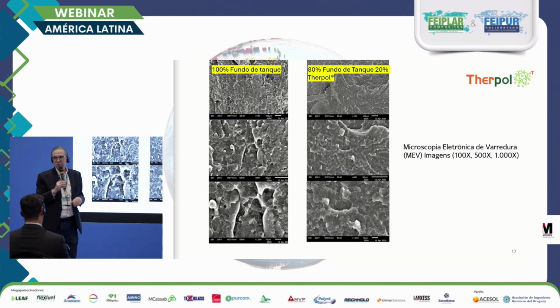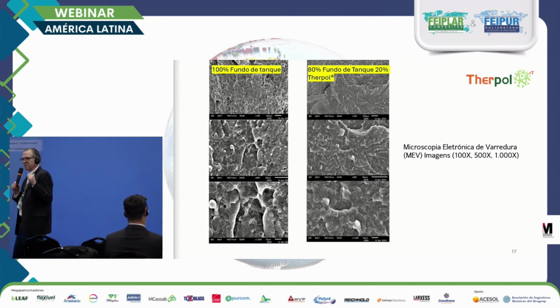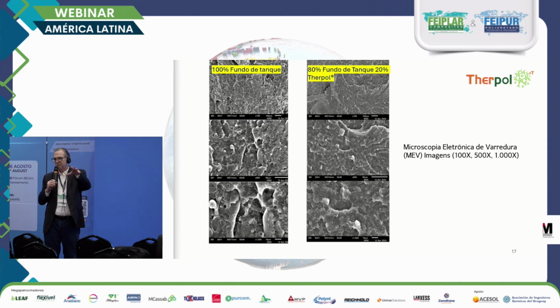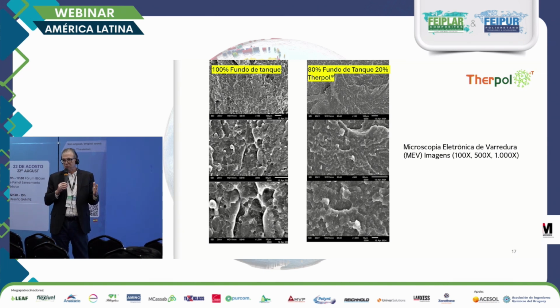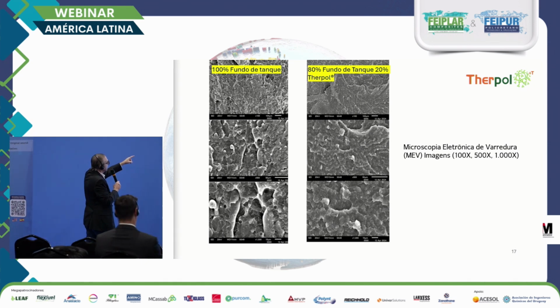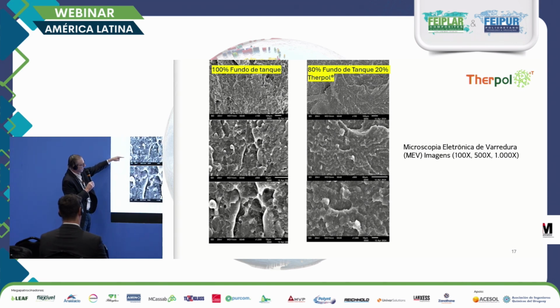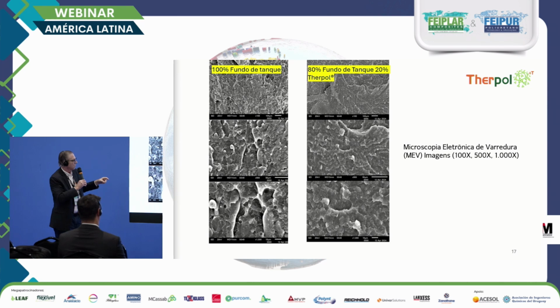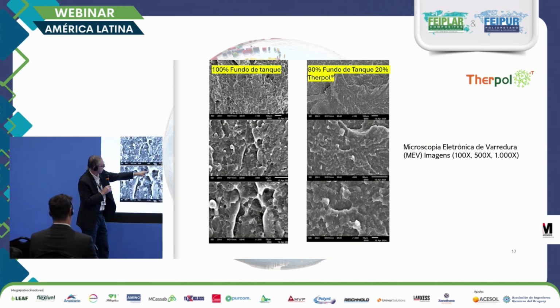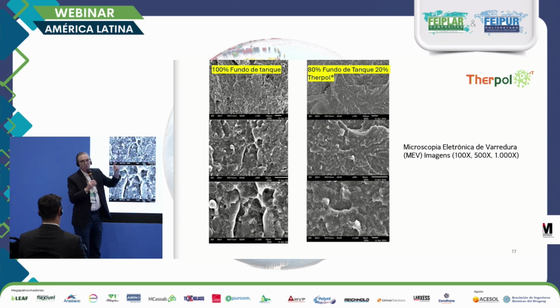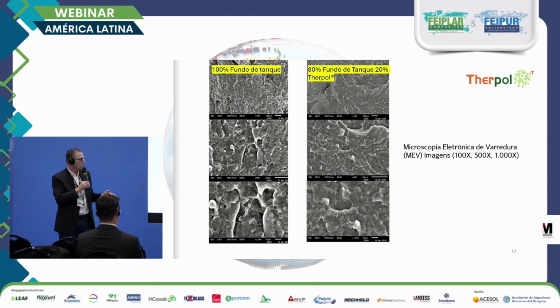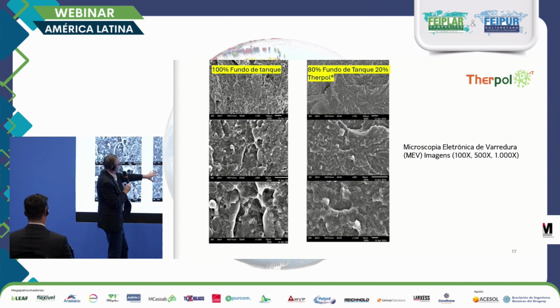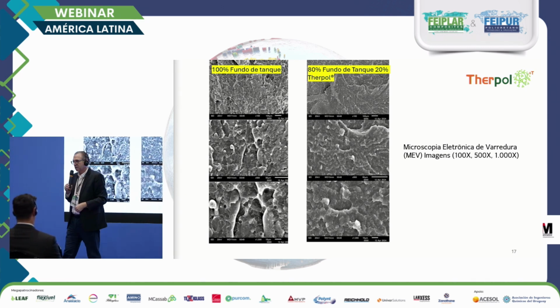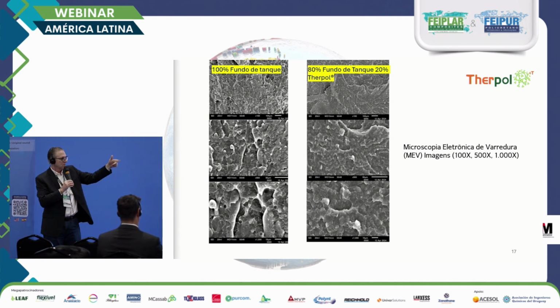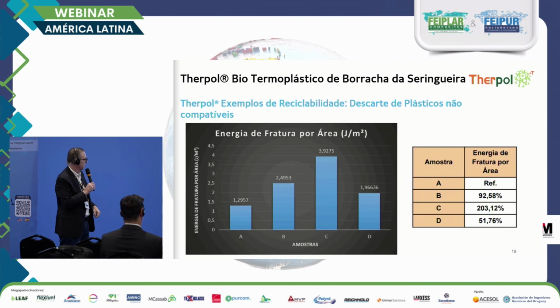These images show, these are microscopic images, and this was carried out at the university. We looked at the tank bottom, that mix. We injected a plate, we broke it, and on the fracture site, we analyzed 100 times, 500 times, and 1,000 times bigger. We noticed that without Therpol, there are several holes, and this makes plastic fragile. When we added Therpol, rubber covered these dark spots. So it's very visible what happened here.